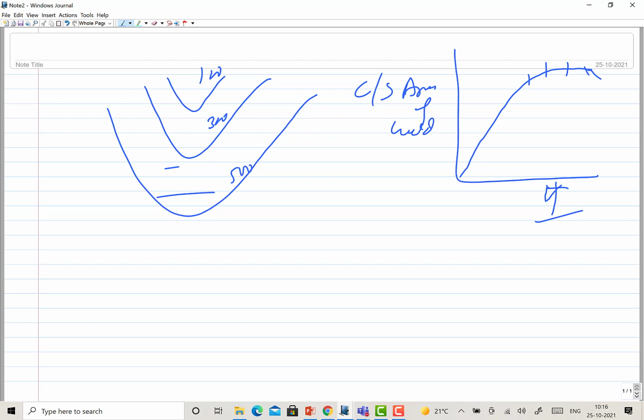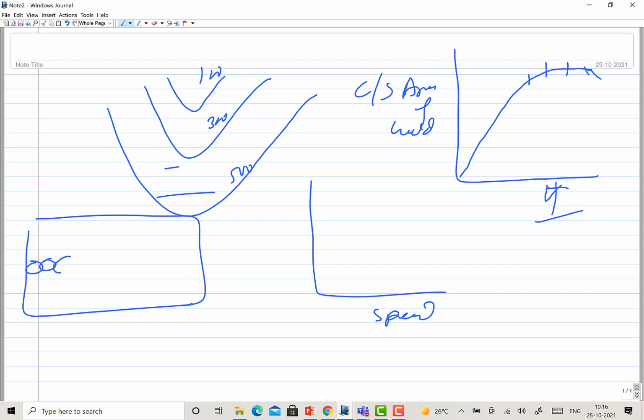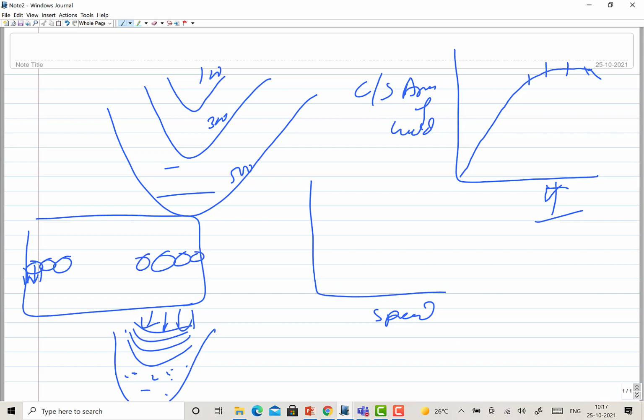Now as far as the welding speed is concerned, there is a need for an optimum speed for maximum penetration. Neither very low nor very high welding speeds will help. Why? Because when you are moving at a very low speed, most of the heat will be localized at a particular surface only. A lot of heat will be delivered, number one, and the heat will be limited to the top only. It will not be able to reach the bottom. At the top you may have molten metal, and most of the heat is taken by the molten metal only. The same is true when you are moving at very high speed, when you are supplying very limited heat.